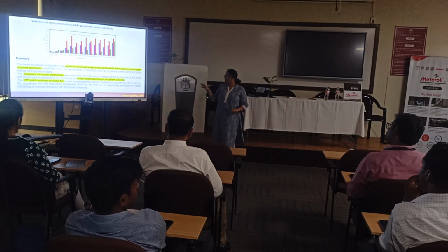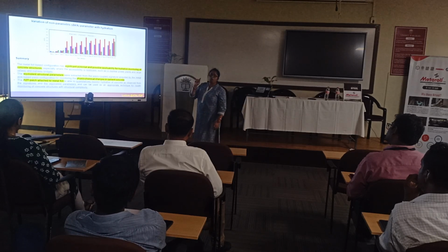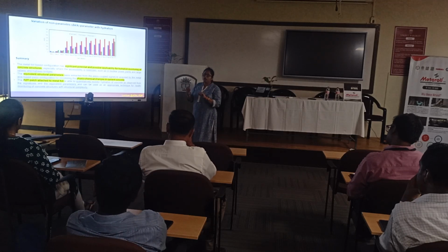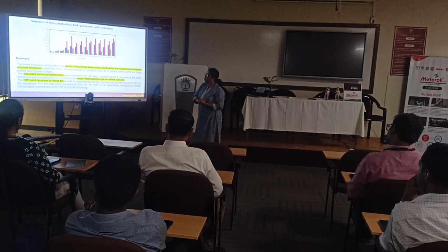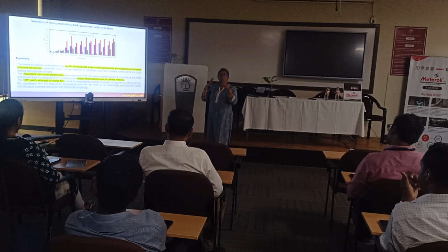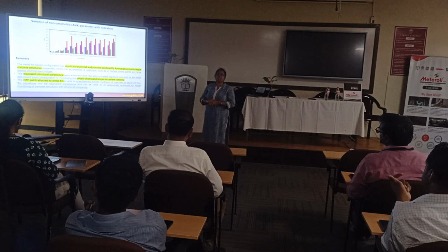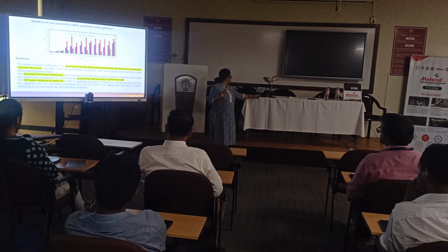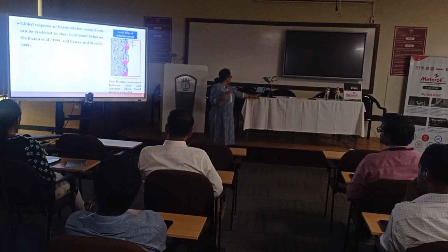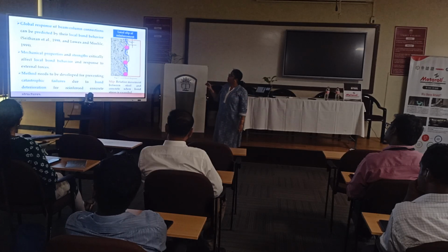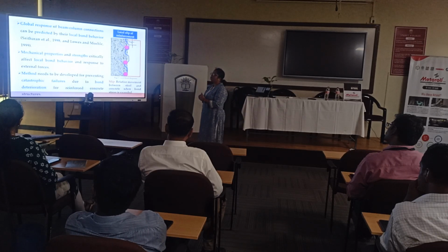And what we understand is, though it's a non-attached configuration, the thinner the metal foil, the better the surface wave propagation and interaction with the structure, to capture the effective behavioral change of the complexity of the hydration process. This is one of the parts that one of my research students worked out. Then later, one of the PhD students' work is about how the bond in the concrete also behaves.